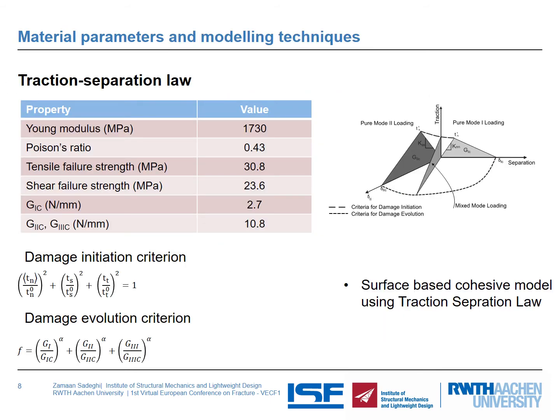Material parameters and modeling techniques. As you can see, the table shows the material properties given by the 3M company for DP490. For the FE technique, a traction separation law was chosen based on a surface-based cohesive model. The damage initiation criterion was quadratic, and the damage evolution criterion was Power law with a power of 1.